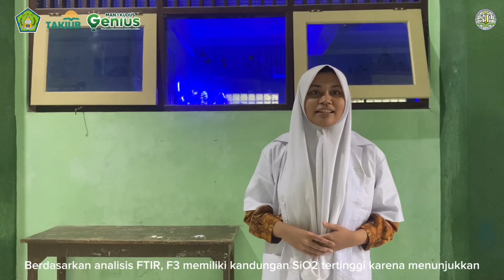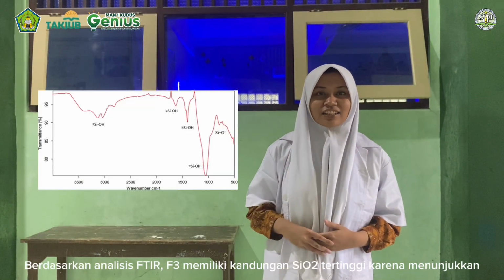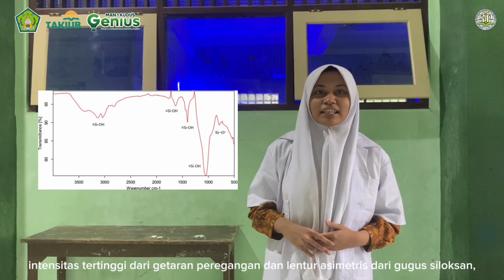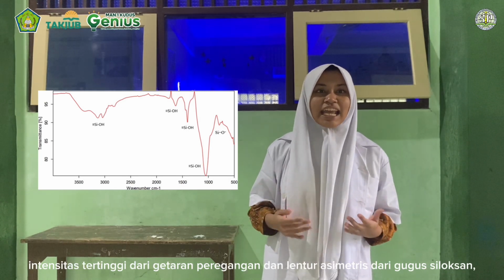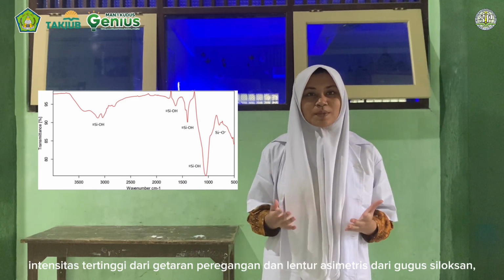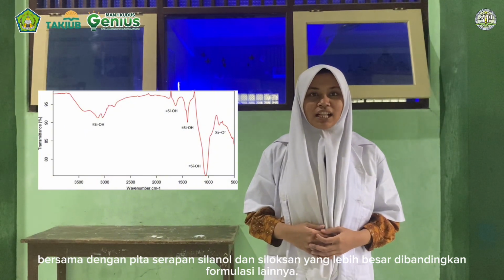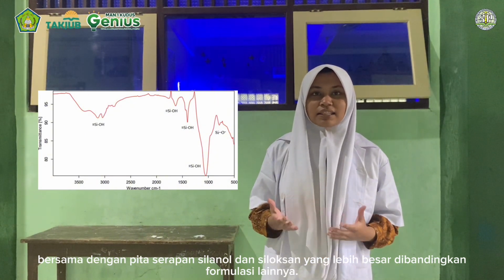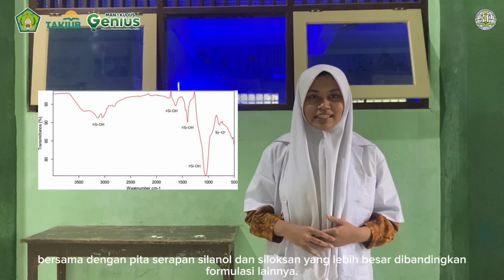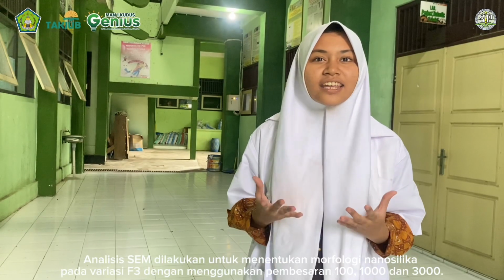Based on FTIR analysis, F3 has the highest silicon dioxide content as it shows the highest intensity of asymmetric stretching and bending vibration of the siloxane groups, along with a greater number of silanol and siloxane absorption bands compared to the other formulations. SEM analysis was carried out to determine the morphology of nanosilica in the F3 variation using 100,